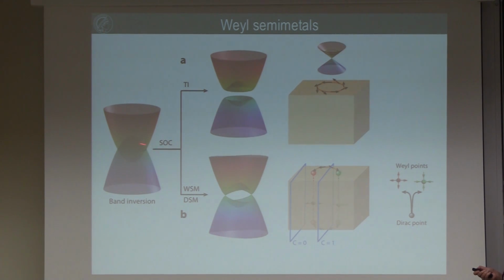What can happen if there's not a lot of spin-orbit coupling—we see this in some Heusler compounds—we have an overlapping area, a nodal line, but depending on the spin-orbit coupling, this can become a forbidden crossing area, and it can open up a band gap, giving a topological insulator, or it only partially opens up because of symmetry, giving Dirac or Weyl semi-metals. So we end up with semi-metals, not insulators.